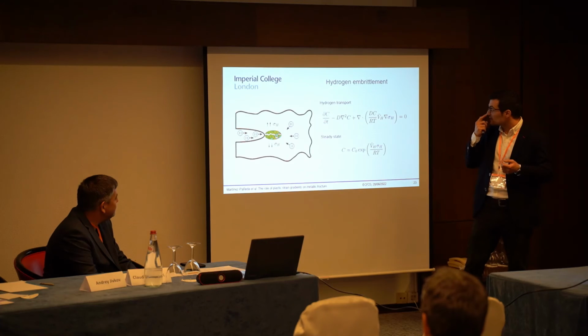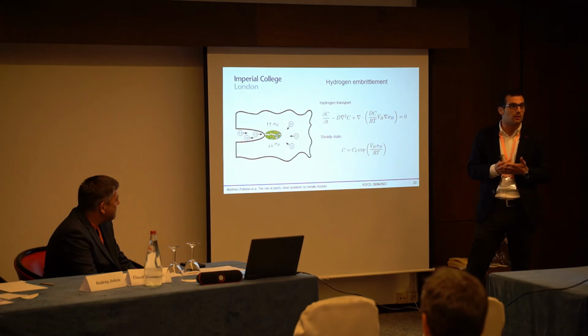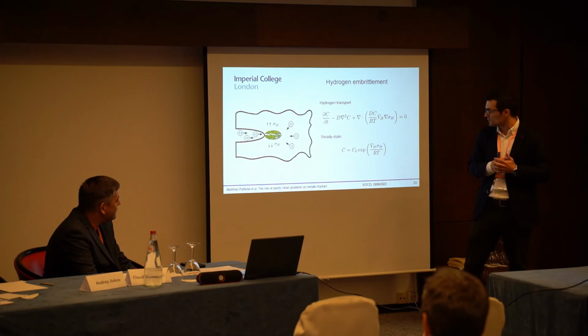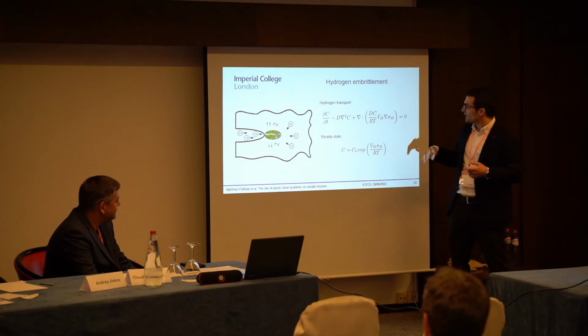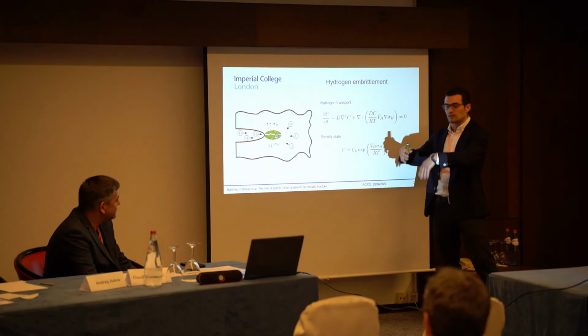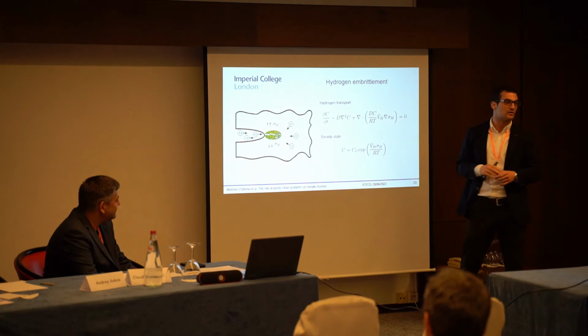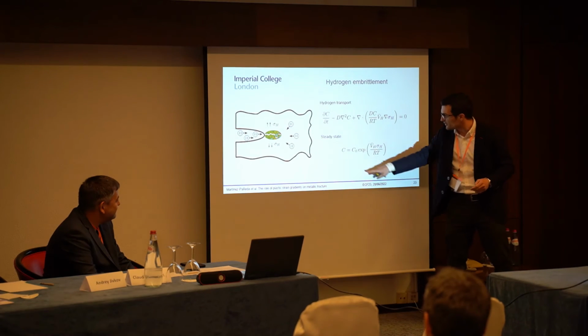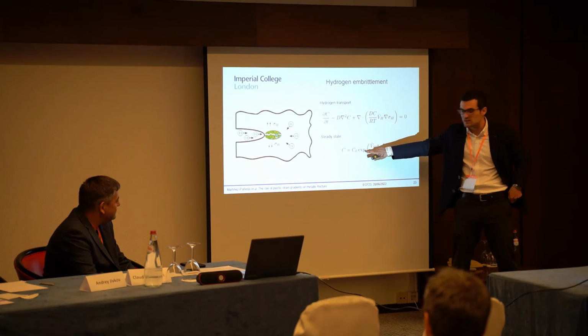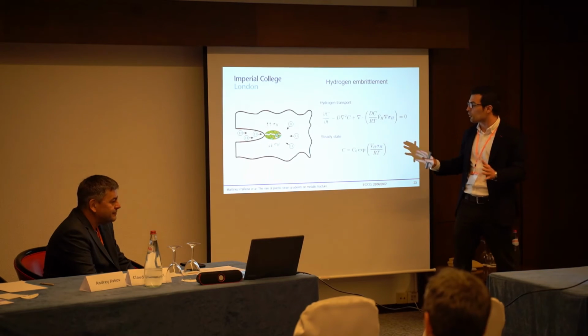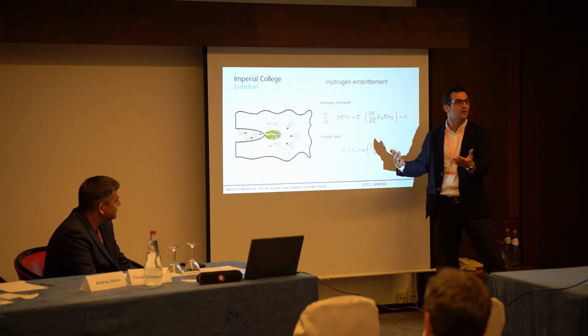And then last but not least is hydrogen embrittlement. This is quite an interesting problem. There's an entire session dedicated to this running throughout the conference. And the idea is that you have hydrogen entering your metal, and the hydrogen transport is driven by gradients of hydrostatic stress. You can see here the steady state expression. You have the hydrostatic stress inside of the exponential term.